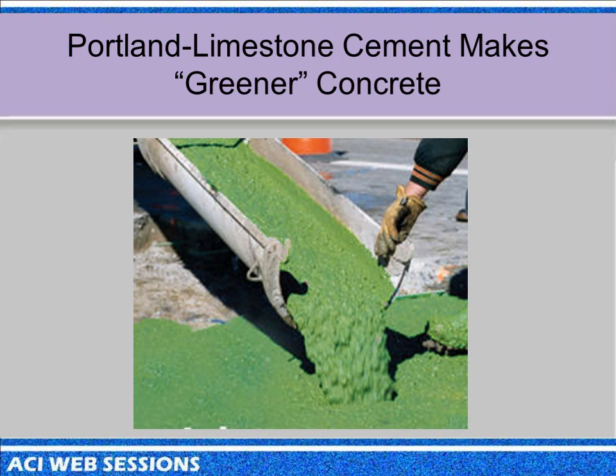And so what we've done, we've got three research programs going: Bob Day at Calgary, Mike Thomas at UNB, and myself, fairly large programs. And we've shown that we've developed a modified C1012 test that you run at 5 degrees Celsius, which is 40 Fahrenheit, and you take your measurements there, and you can show that at those temperatures you will form thaumasite.